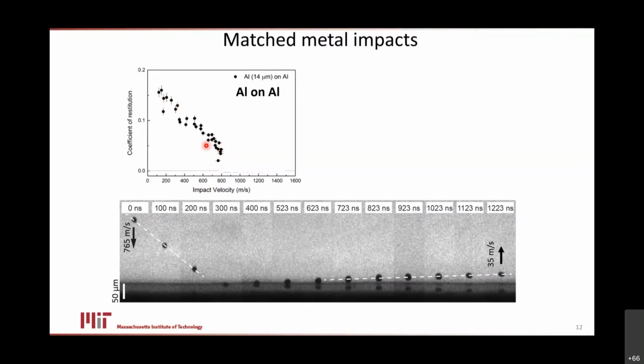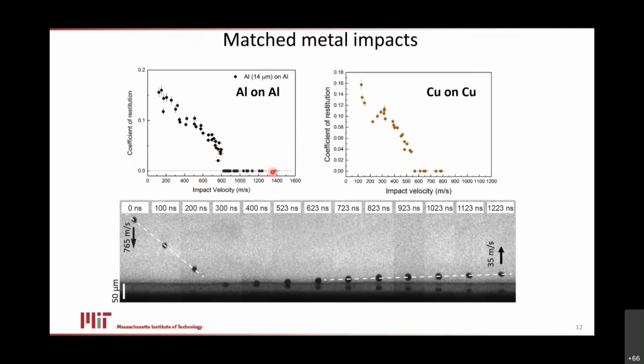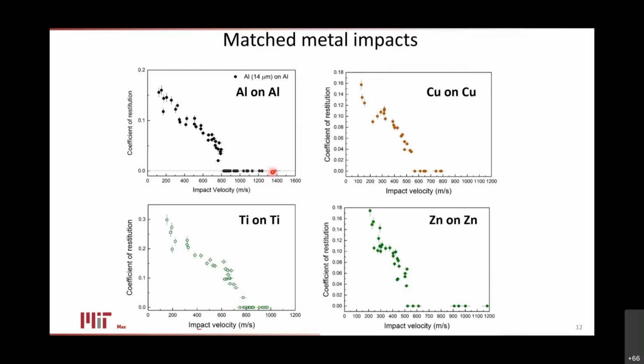And then, of course, there's also new physics that we care about. If we shoot these things fast enough, they don't bounce at all. They stick to the substrate. And understanding that sticking really is important in the field of cold spray. So we do this not just on aluminum, but on alloys and on other metals as shown here. Again, high throughput, you can get a lot of data reasonably quickly. They're all similar, but of course different in their details. What we'd like to understand is, what are the physics controlling those details? How can we predict the onset of bonding, for example?